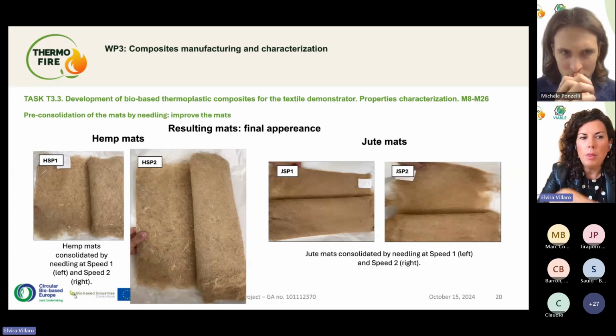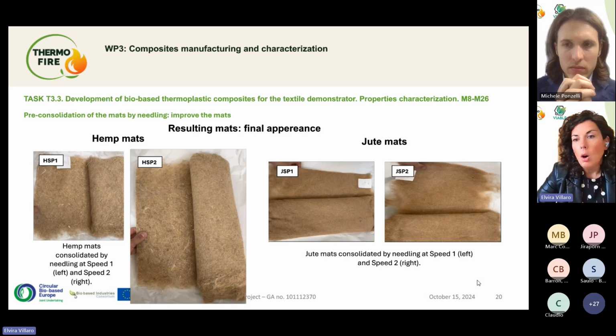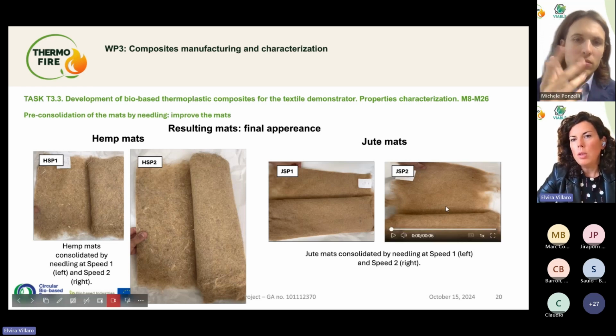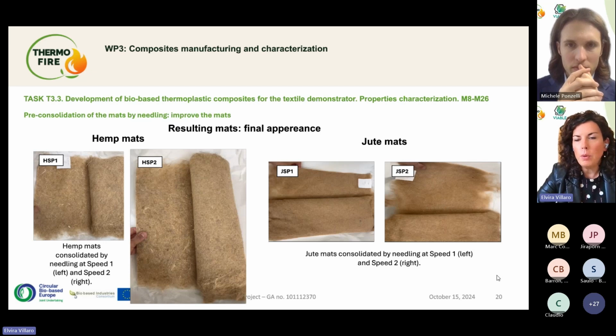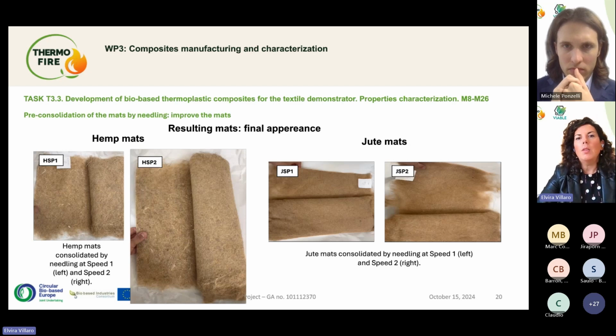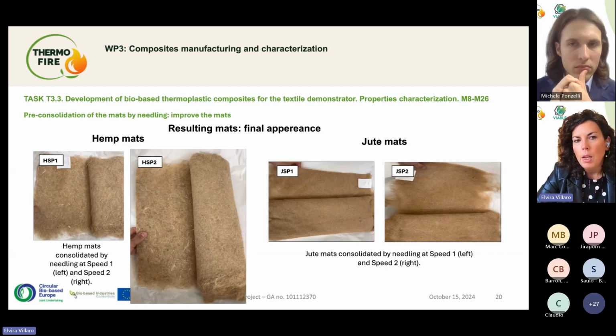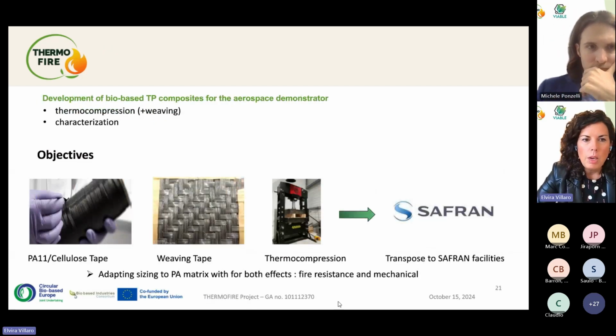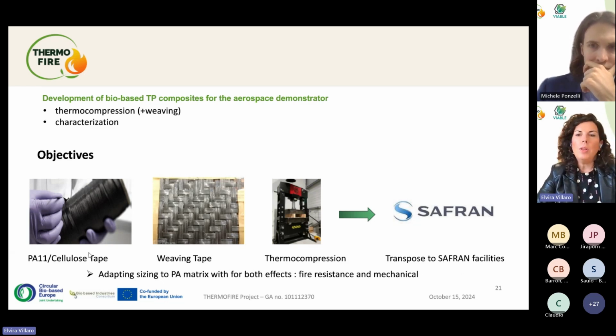And then, of course, we will make the composite with the polyamide 11 for the different use cases. In the case of the aircraft, of course, we are not going to achieve the mechanical performance required with these mats, with these fibers. So in this case, we are using cellulose fibers, making thermoplastic prepregs, working with polyamide 11 to prepare the structural components. This is what I was explaining before. These are the tapes that we are developing with cellulose and polyamide 11. We will do this kind of weaving, and by thermocompression, we will make the demonstrator for the aircraft sector.